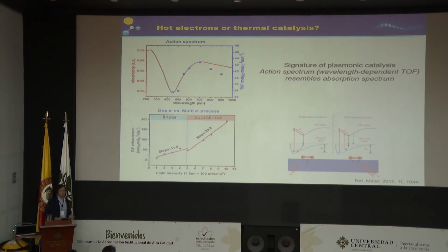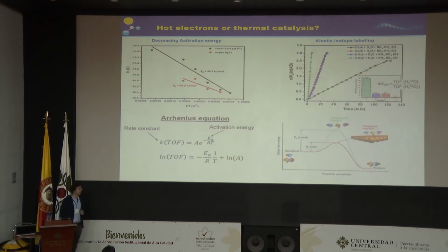If we think about the difference with semiconductors, for example, in photocatalysis, we excite with one photon usually one electron and one hole, so we have one type of interaction. With plasmonics, one photon really excites many electrons, which of course forms the plasmons, and therefore the formation of hot electrons results in many hot electrons per photon. And indeed, we have preliminary results that show more than 100% quantum yield in the reaction, which is double what has been reported for silver.